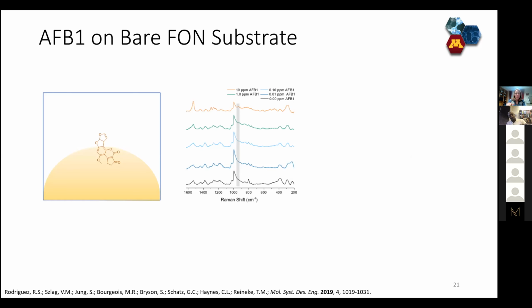So you're seeing some Raman spectra in the middle here. The black one is a negative control, so there's no aflatoxin there. And then as you go up, you're going to higher and higher concentrations of aflatoxin. And if you look in that little gray bar, you might see that there's like a tiny new peak that shows up, but it is very small. And if we go through and analyze that peak, which is attributable to aflatoxin B1, a specific ring breathing mode, what we see is that we can actually distinguish 1 part per million aflatoxin from 0. That's what the statistics tell us.